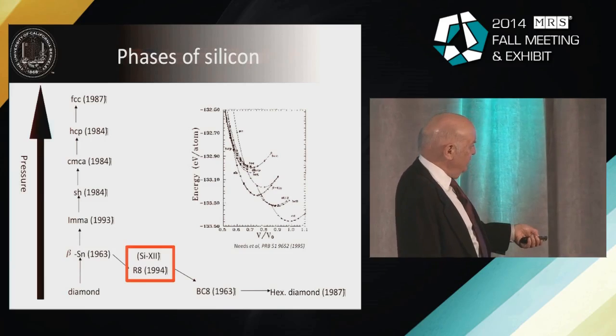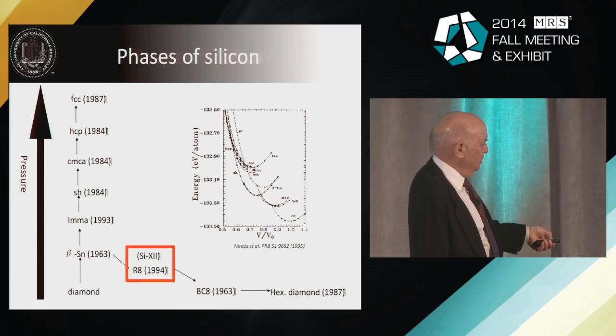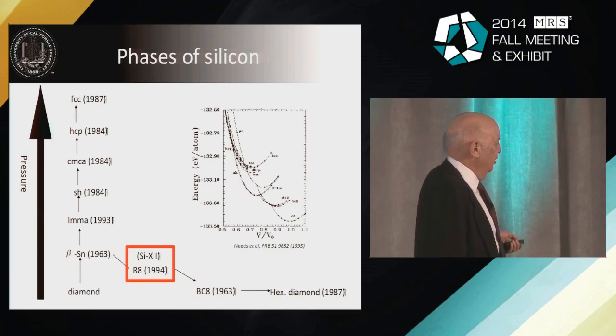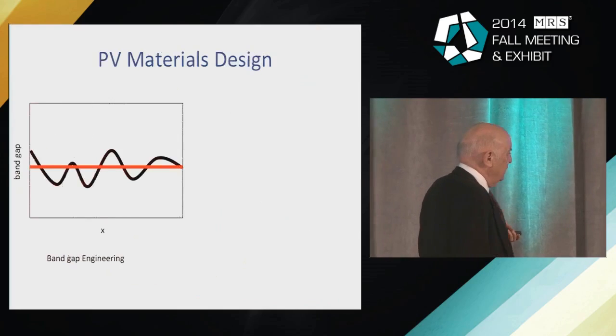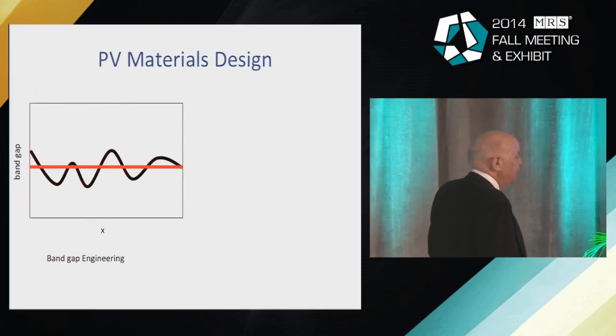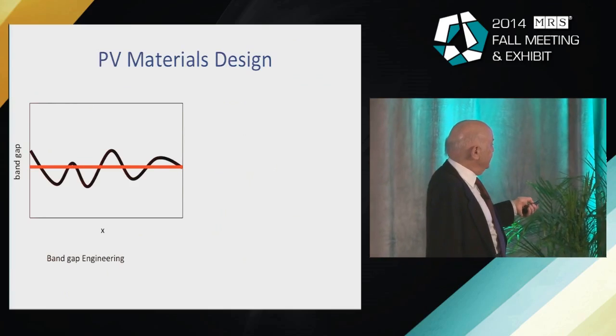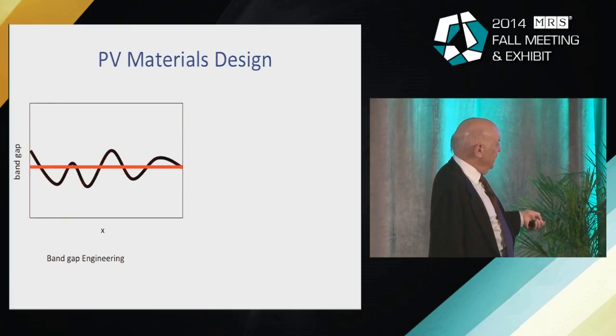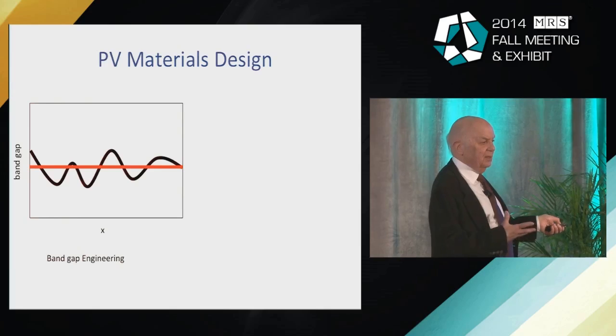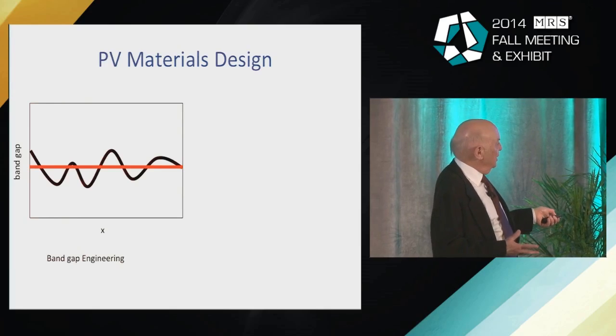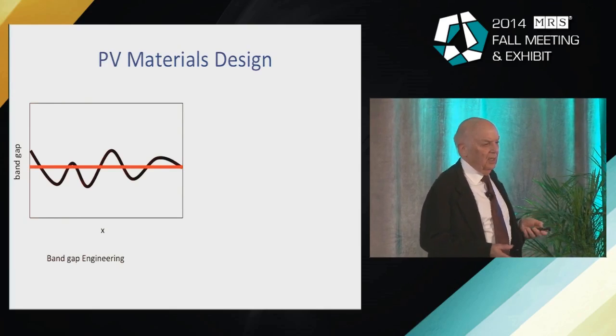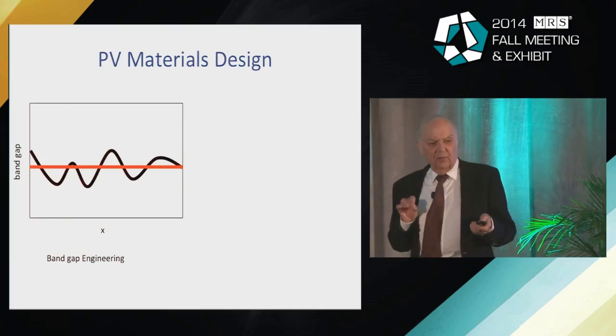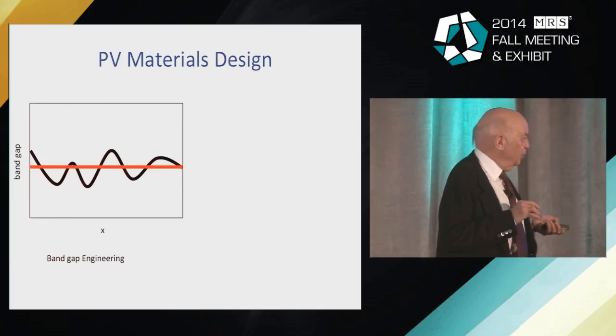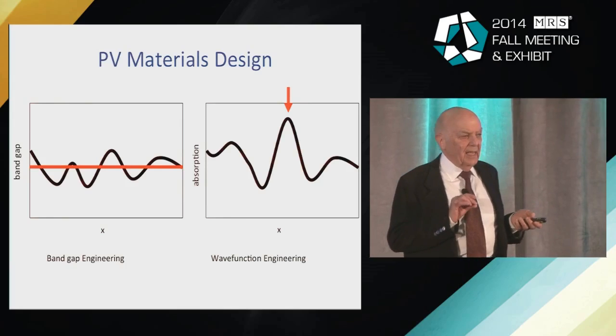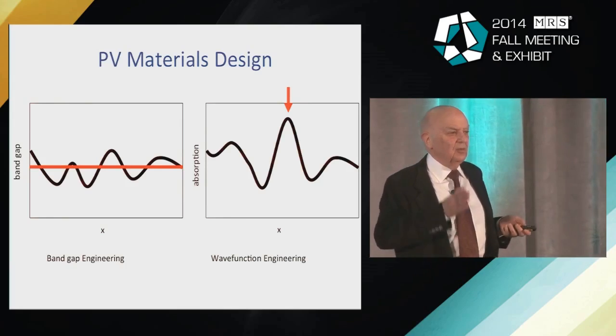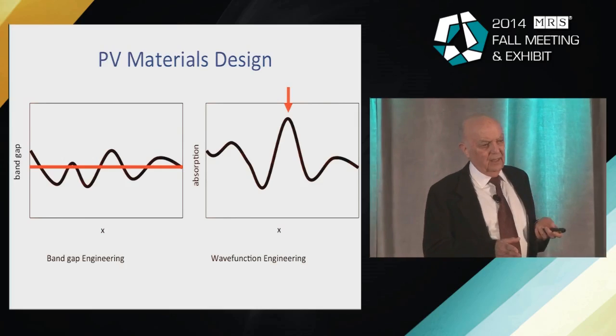I'm sure there are more that people are coming up with all the time. So, for example, if I take this material, I won't show you its structure, silicon in the R8 structure. The idea is the following. With band gap engineering, you try to tailor the band gap as a function of either alloying things together or doing various things so that the gap is in the right range. But the point is not so much that you want the gap in the right range, you want the system to absorb the sunlight in the right range.